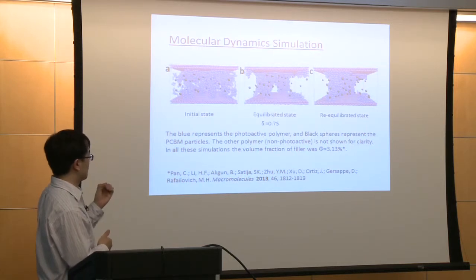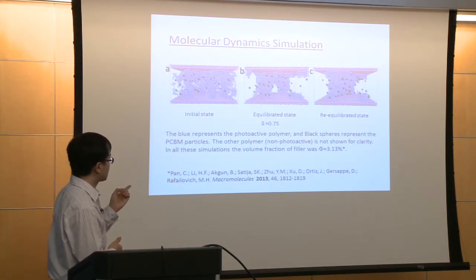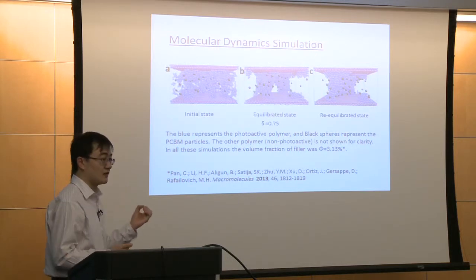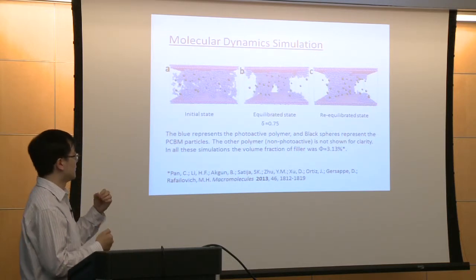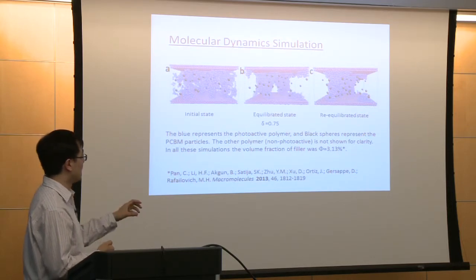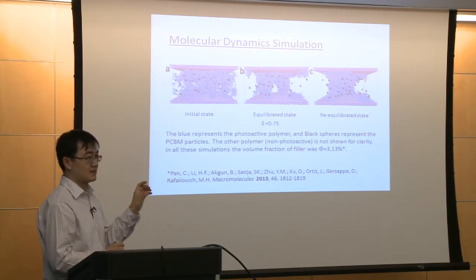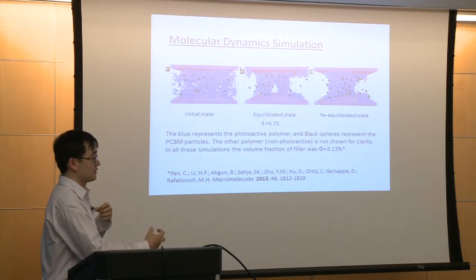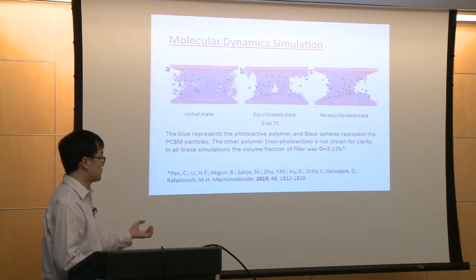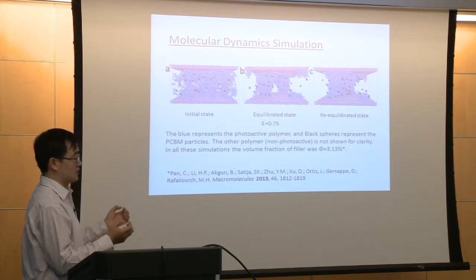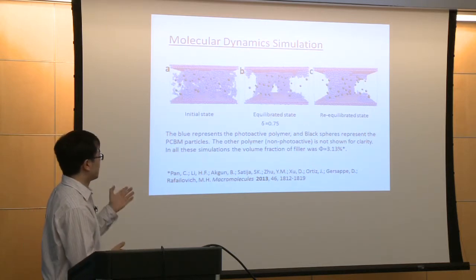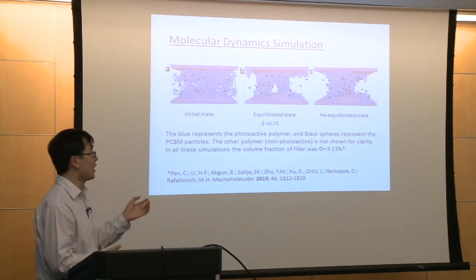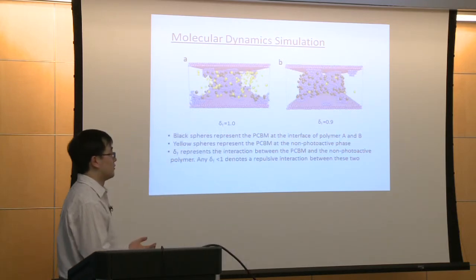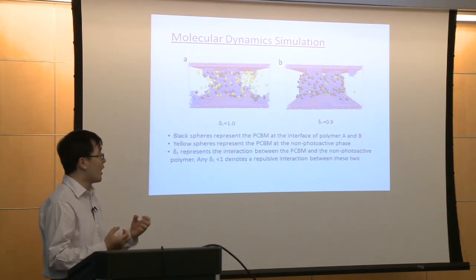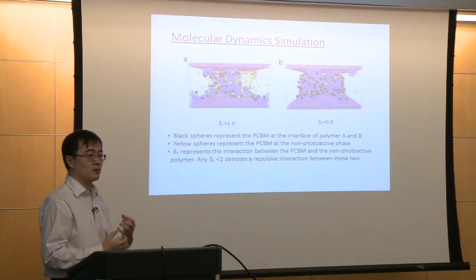But one thing you need to keep in mind is here the delta is equal to 0.75. What's delta? Delta is the interaction between the P3HT and the secondary polymer. So when the delta value is less than 1, there is a repulsive interaction between the P3HT and the other polymer, which means they don't like each other. So that's the important factor in how the column structure can form. Okay, so now we know if the 2 polymers have repulsive interaction, they can form column structure.